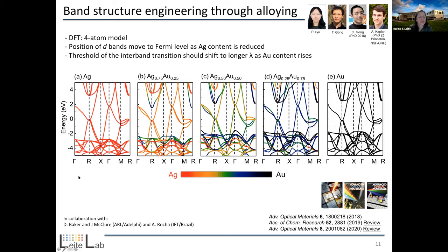So basically, what we did here, we realized that we needed to actually calculate the band structure for this binary mixture. So again, as an example, I'm showing you here silver and gold, and here's what we see. For pure silver and pure gold, here in red and black, respectively, we're talking about the textbook figure. Okay, so let's focus on the gamma point. That's enough for us to learn a lot about what's going on. So what we can see here is that as we increase the amount of gold, the position of the d band moves towards the Fermi level. So that's essentially what we're seeing.